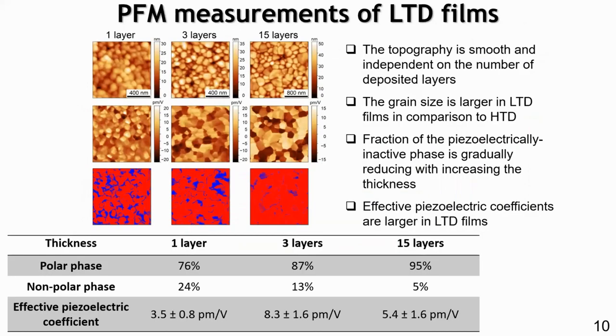Later we tried to do the same measurements on the low temperature film, and we see that here the situation is absolutely different. In the beginning, in the first layer films, indeed we have some small areas with piezoelectrically inactive phase. It can also be caused by the conductivity across the boundaries of the grains. But later, when we deposit additional layers, so 3 layers and 15 layers, you may see that the amount of the secondary phase significantly decreases.